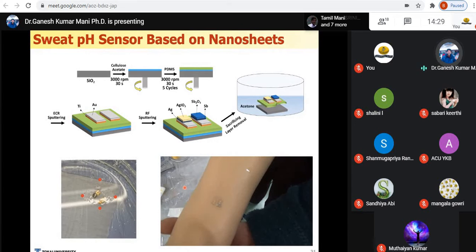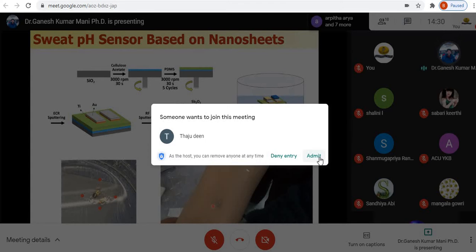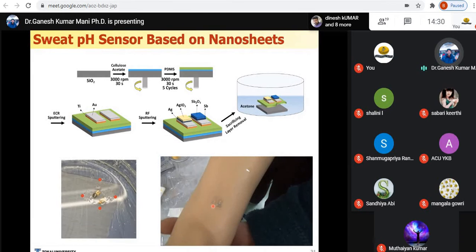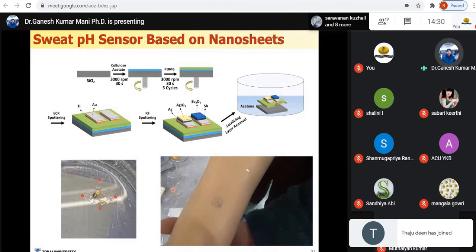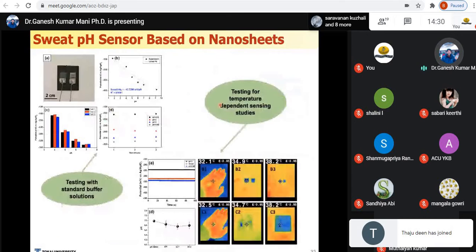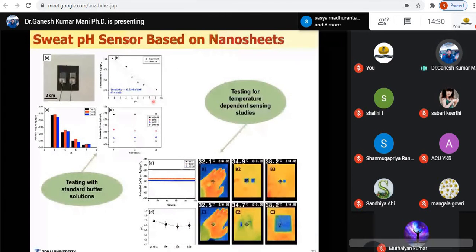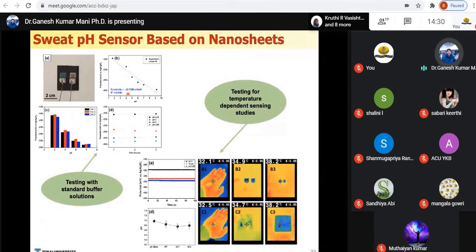Here, the sensor is transferred to an artificial forearm, and even after several bendings and twistings, the nanosheet withstood it. It did not tear, and visibly no crack was found. Then we tested the pH measurements using a standard procedure in the laboratory. First we measured with standard pH buffer solutions and estimated the sensitivity at about 74. Even after 3 trials, the sensitivity was the same, and the sensor has good stability too.